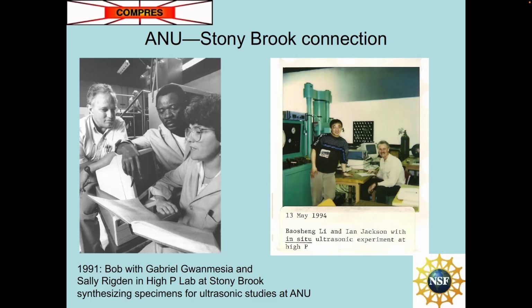So Jackson actually came to Stony Brook for a few months, and with Baosheng incorporated the ultrasonic approach developed by Jackson and his colleagues into our multi-anvil apparatus at Stony Brook. We call this a Kennedy press because it was originally one of the ones that was in George Kennedy's laboratory, was bought by the chemistry department at Stony Brook, and we took it out of surplus and installed a Walker-type high-pressure module inside it. Next slide.